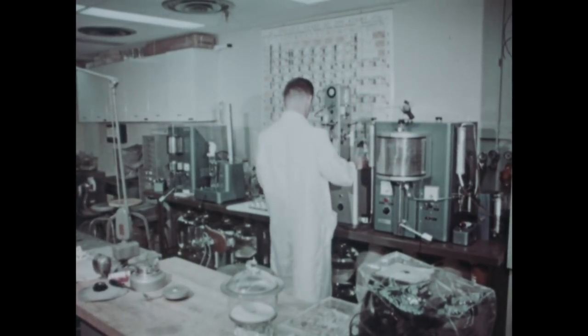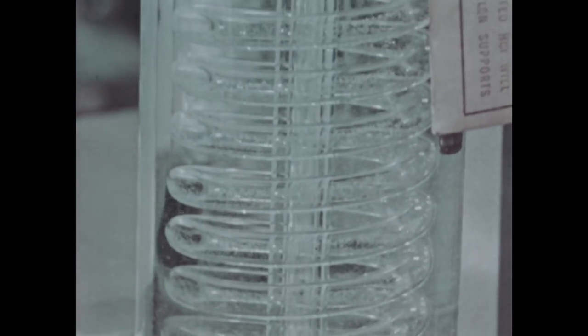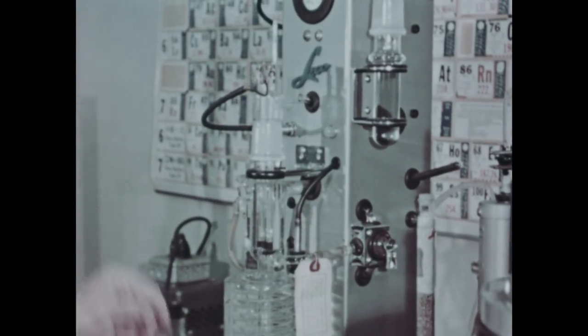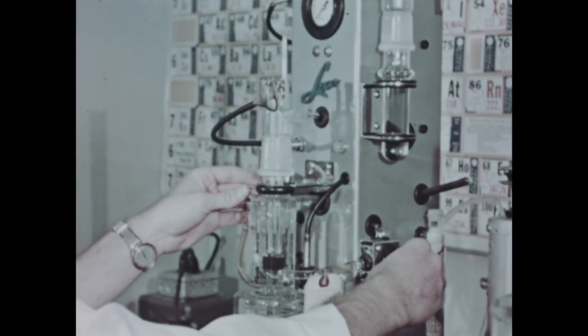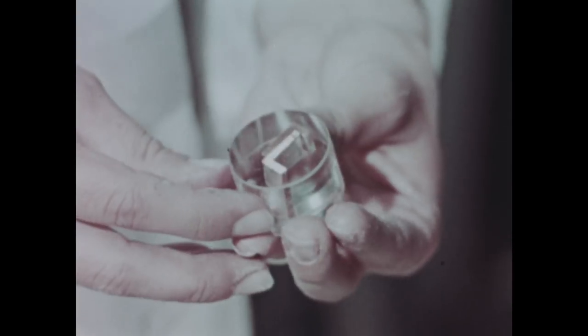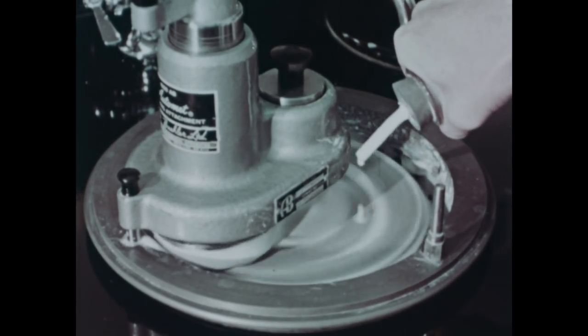Since the quality of the copper must be extremely high, its purity must be carefully checked. In the metallurgical laboratory, oxygen analyzing equipment determines the amount of oxygen in the copper. Copper specimens are cast in plastic, ground, and polished for microexamination.